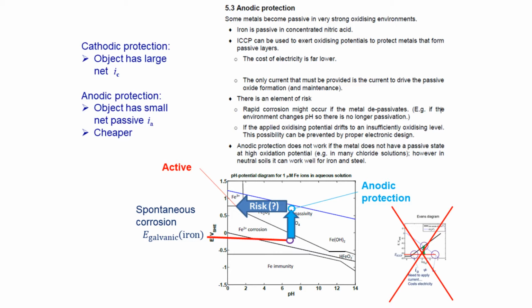Now that's a problem that is partly mitigated with modern electronics, because we can monitor what anodic current is being supplied to the metal. What should be supplied is a very small current to drive the repassivation of any of the metal which becomes scratched and needs an anode current to repassivate it. If we're suddenly supplying a large current, we can suspect that there is active corrosion going on, and then the system might shut down so that it doesn't extensively damage the thing that's being protected. But there is this complexity.